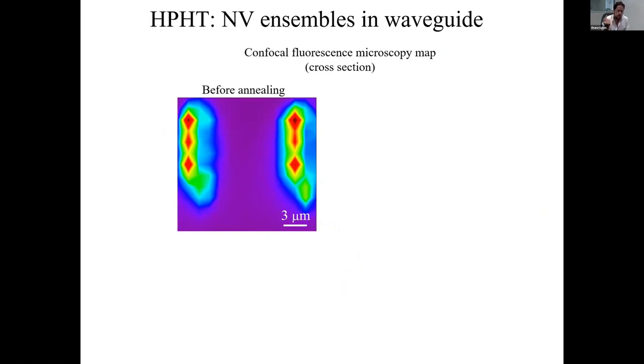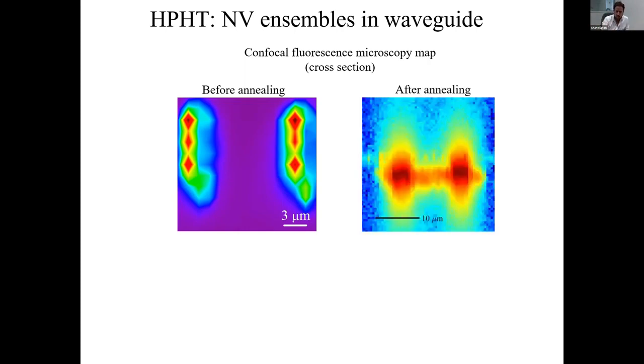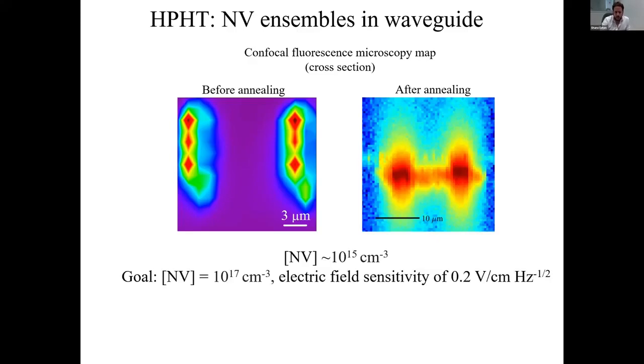But what we really like for our quantum sensing application is this NV emission to come from the middle, where we have this overlap with the optical waveguide mode. After thermal annealing, it caused these vacancies that we produce within the sidewalls to mobilize. And what we found is a strong emission also within where we have overlap with the waveguide mode in between these two elliptical sidewalls. And so what we estimated is we could produce an NV concentration of 10^15 inverse centimeter cubed. Our goal is to boost that by a factor of 100, which would give us the record high electric field sensitivity.